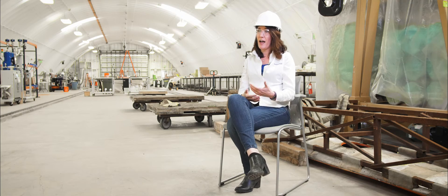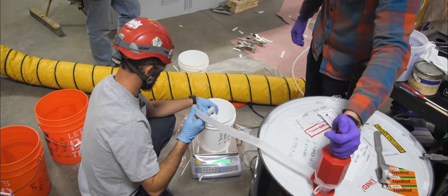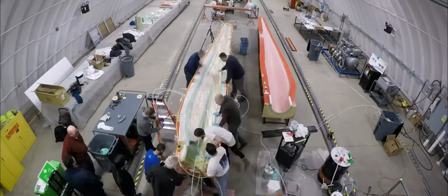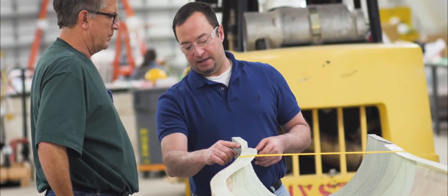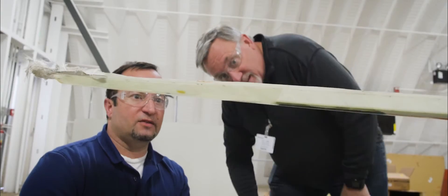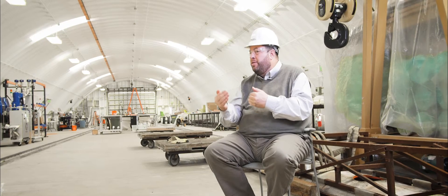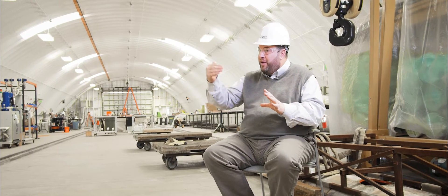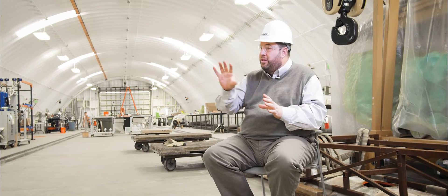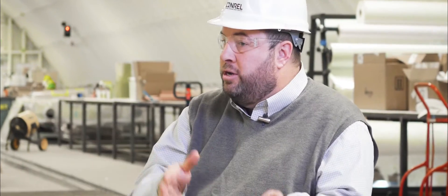To give an example of how much faster it is: we did a shear web infusion using the Elium 188 system, and we were able to get a wet-out of the entire part in about 30 minutes. Then we were able to demold and have full strength properties in three hours, which is exceedingly fast compared to thermoset materials. A lot of the different learning from this project helps us advance the Elium thermoplastic resin system towards commercialization with our industry partners.